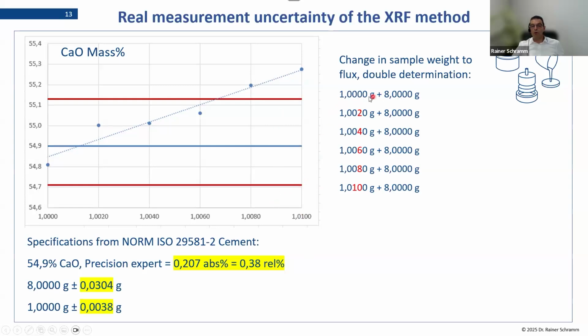And that means the first sample, which is perfectly weighed, is this point. So it's a double preparation, and I show you the mean value. And you see now I increase my sample weight. This is then 2 milligram more, and 4 milligram more, 6 milligram more. So you see all are still inside the error, but then with 8 milligram I'm out. So you see that in a certain way, it allows me to make an error in weighing without really affecting the final result. And this is the one from the sample. If I would change the flux, I could increase up to 30 milligram error without leaving my error range.